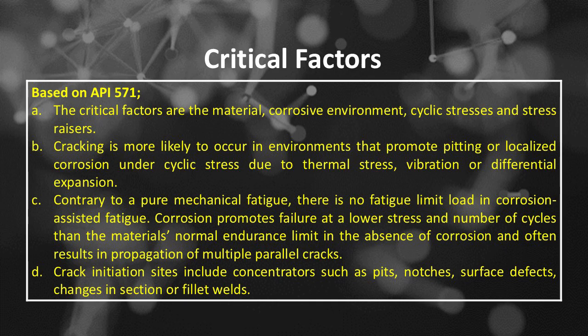Number C, contrary to pure mechanical fatigue, there is no fatigue limit load in corrosion-assisted fatigue. Corrosion promotes failure at a lower stress and number of cycles than the material's normal endurance limit in the absence of corrosion and often results in propagation of multiple parallel cracks. Number D, crack initiation sites include stress concentrators such as pits, notches, surface defects, changes in section or fillet welds.